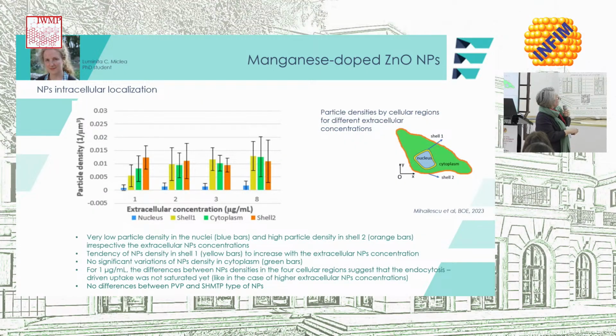And then we saw that at very low particle density, nanoparticles can be found in the nuclei of the cells. Here, almost nothing. It was at the threshold of the method to identify the nanoparticles inside the nucleus of the cell, while at high particle density, the orange bars were present close to the inside of the membrane, let's say, to what we consider to be the edge of the cell. And there was a tendency of nanoparticle density in shell 1, this one around the nucleus, to increase with the extracellular nanoparticle concentration, but not so much variation in the case of cytoplasm.